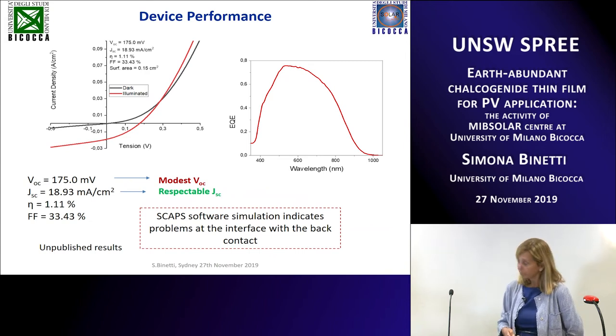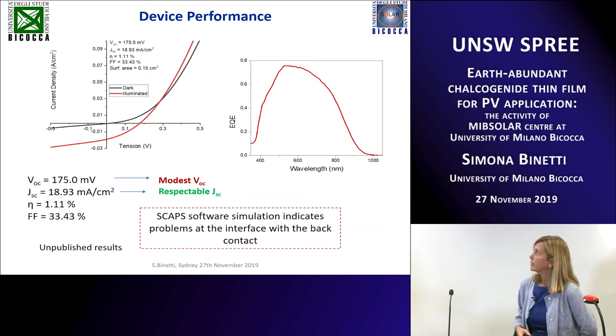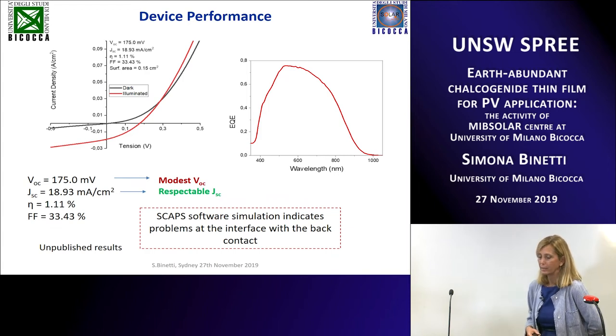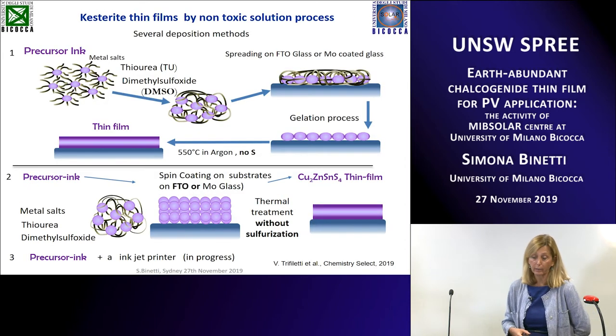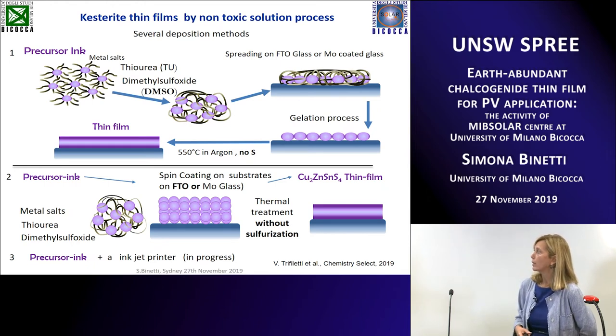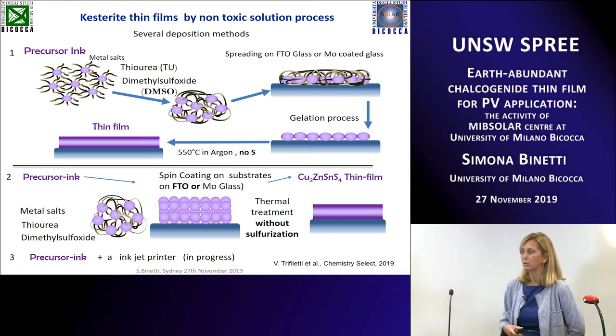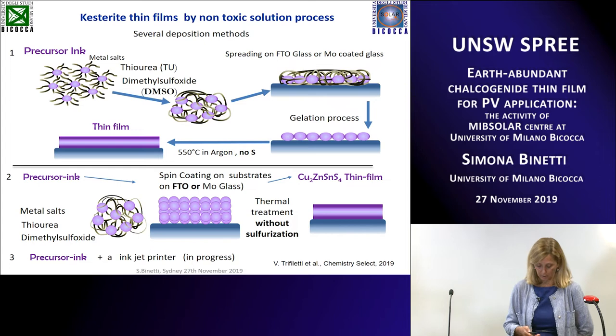back contact. So by this method, we can very easily deposit the Kesterite thin film just by drop casting with a gelation process, or we can control the viscosity and use this molecular ink for spin coating deposition, or our idea is to optimize the viscosity in order to use this precursor ink for an inkjet printer deposition system.